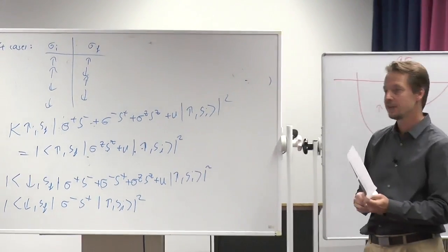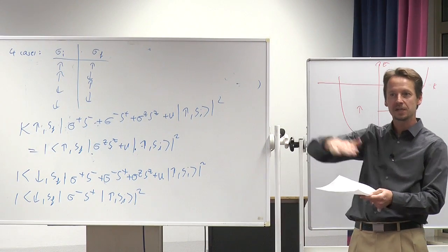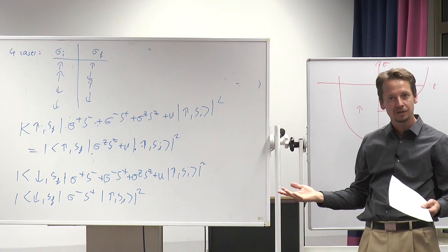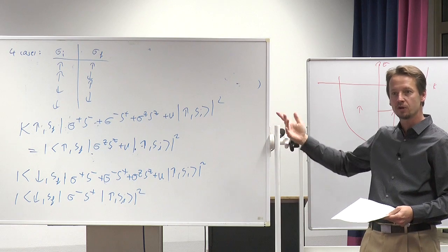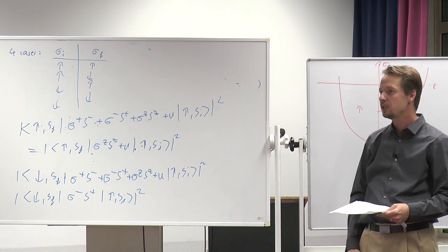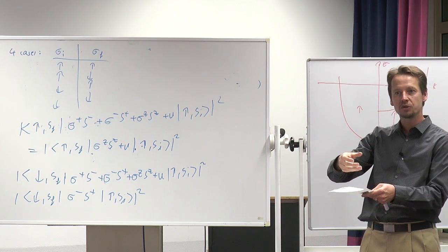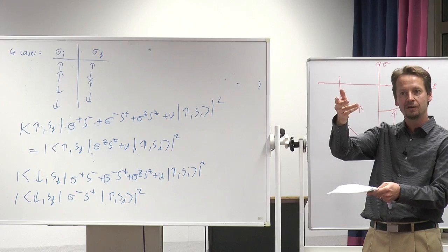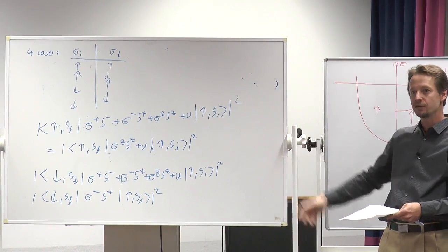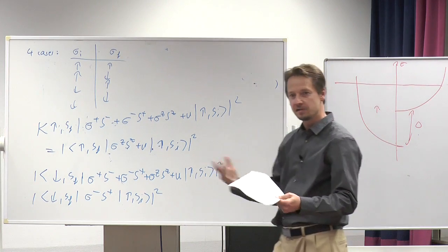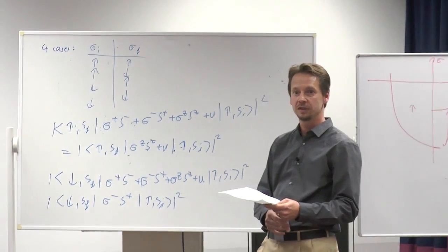If you want to calculate the occupations of these 6 M states I have for my manganese in a finite magnetic field, you have to keep track of these processes and do a bookkeeping of which state you are in. Maybe you start in the ground state, you run an electron through, and with a certain probability it goes into the first excited state. Maybe now you do a relaxation mechanism or not. Then you keep track of this and calculate the current as a function of the occupation of these states, following these rules.